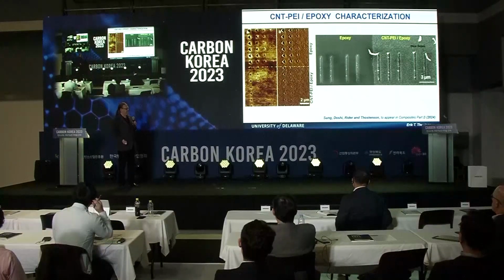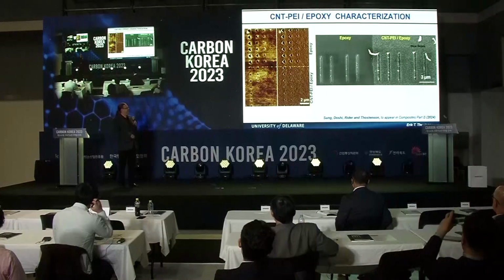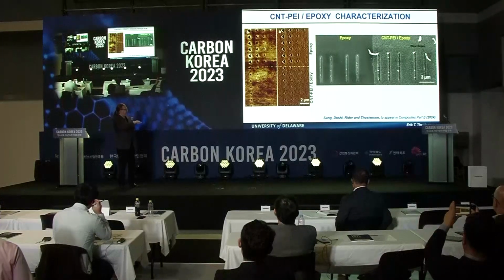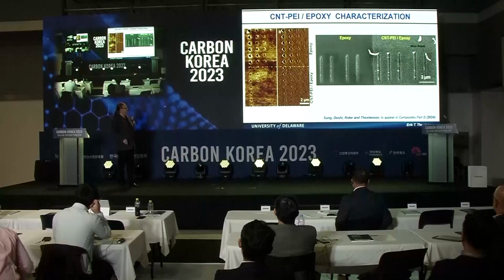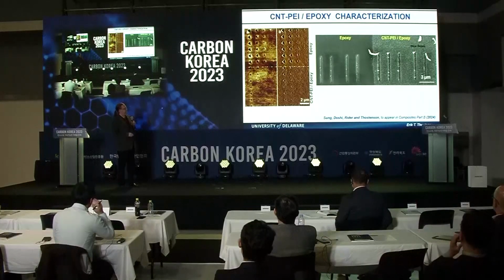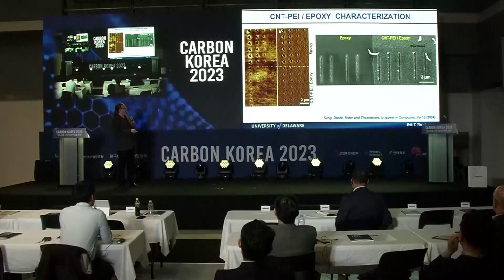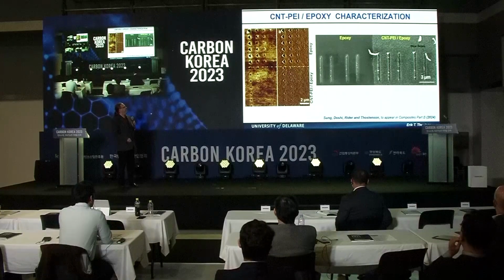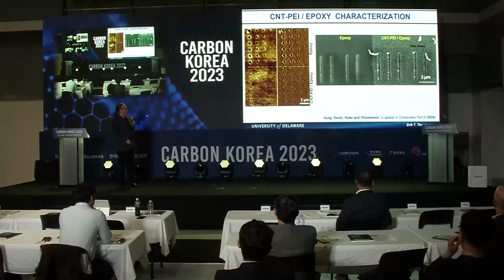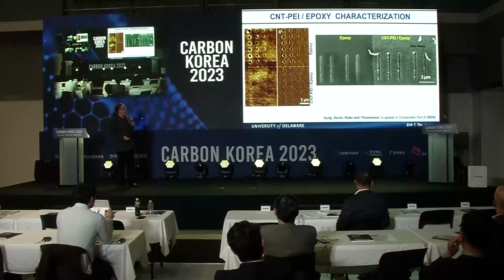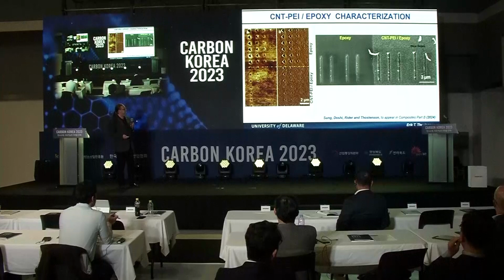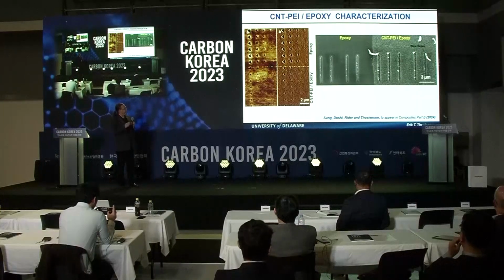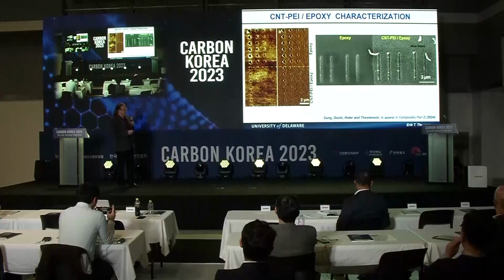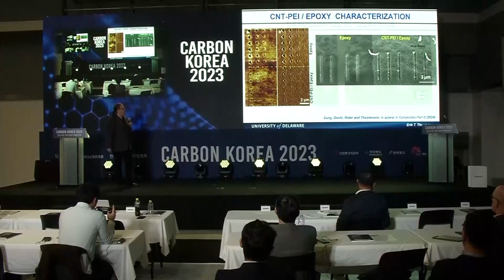This is just some nanoscale characterization. On the left-hand side, just bulk epoxy, and then also our nanocomposite, at a relatively high nanotube volume fraction. And you can see the indents are much shallower, so we're stiffening it. On the right-hand side, you also see that there's increased toughness, and that's a nano scratch test. Those vertical lines that you see, and you see that debris, and if we move in closer, you'll see a lot of pullout.